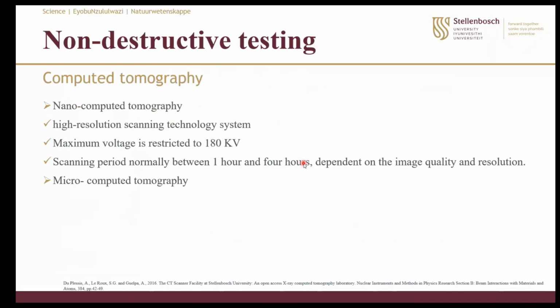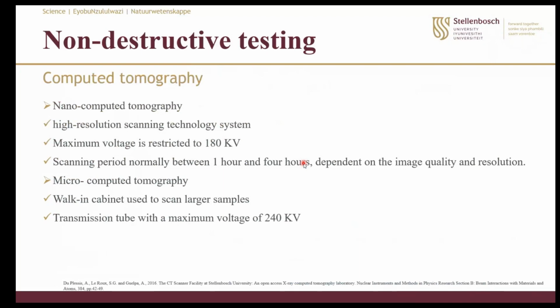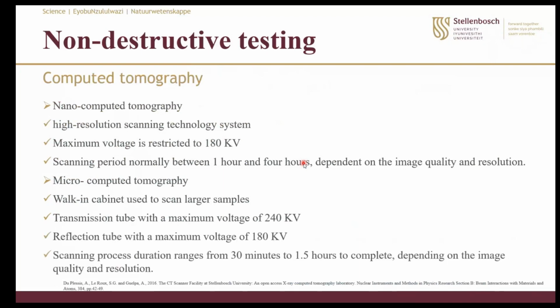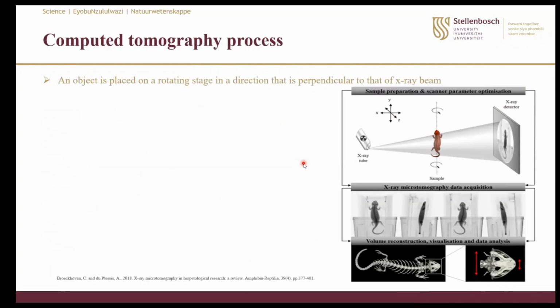And then the next one, and the mostly used one, is the microcomputed tomography. It is basically a walk-in cabinet that is designed to be used on large samples with diameter between 10 millimeter and 300 millimeter. It has a transmission tube and a reflection tube. And the scanning process duration for this one normally lasts between 30 minutes and 1 hour and 30 minutes.